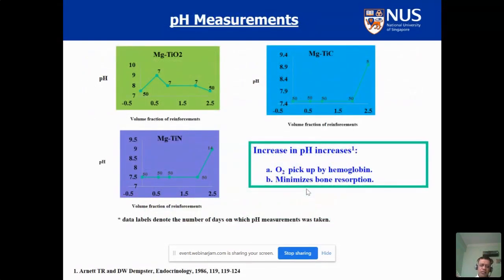Having said that, not all reinforcements work in a similar way; different reinforcements work in different ways. For example, if I go for the Mg-TiO2 system, the green plot here, you will see that if I had to choose, I will choose 2.5% of TiO2, because for 50 days it does not affect much of the pH. Increasing the pH means more corrosion. So I will choose 2.5% TiO2, while I'll choose only 2% of titanium carbide, as you see in the sky blue graph. And in the purple one, I will again choose 2% of titanium nitride. So essentially, once again, nano reinforcement helps, but for the different types you have to do the tests and ensure what amount is suitable.